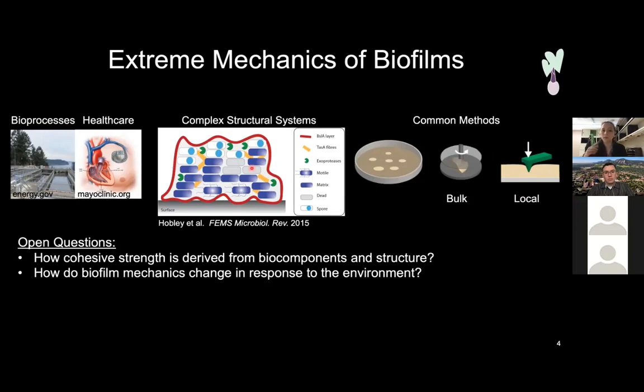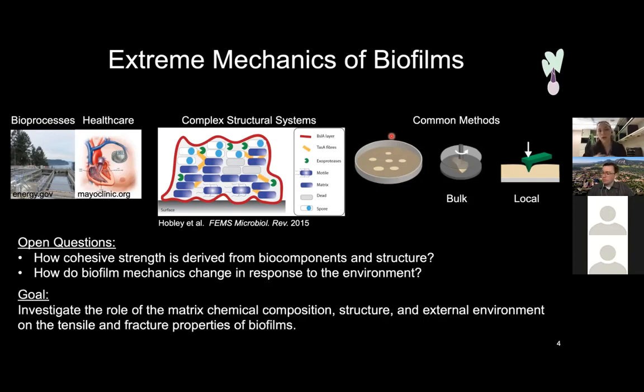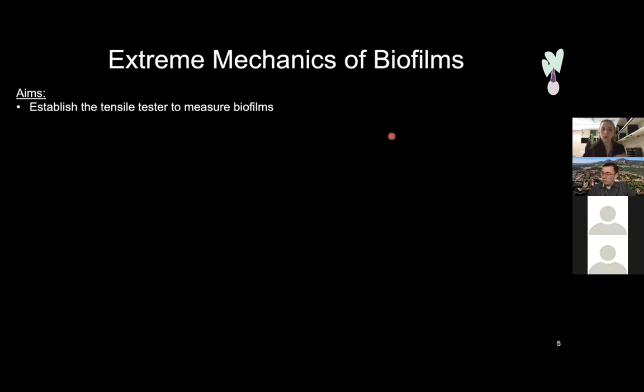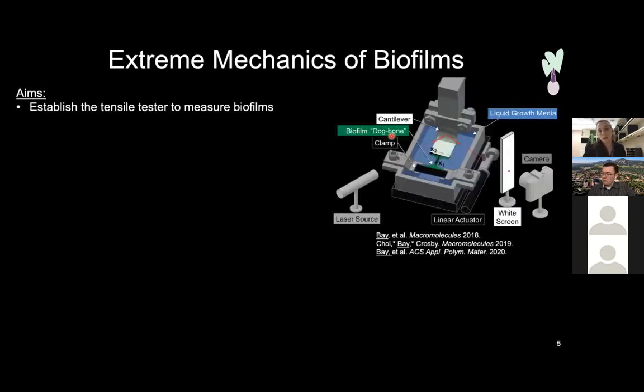And then can we further understand how they respond to the environment? If you think about these plates controlling the properties, they've shown that the osmotic pressure of these plates matters. So really, the first area of my group is going to investigate the role of the matrix composition through gene knockout, and then look at the hierarchical structures and the effects of the external environment on these tensile and fracture properties. To do this, we're going to use the tensile tester that I developed in my PhD, the cantilever-based system, but now we have an opportunity to change out the dog bone shaped film for a biofilm and put it on a liquid supported bath where we can control what the environment is.